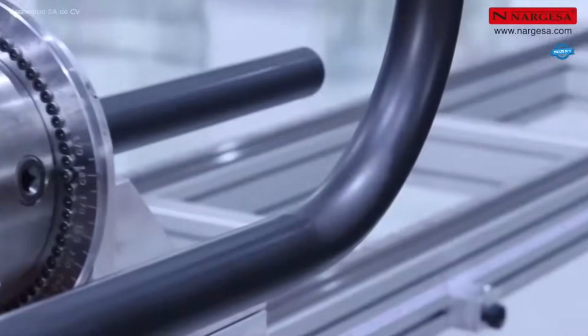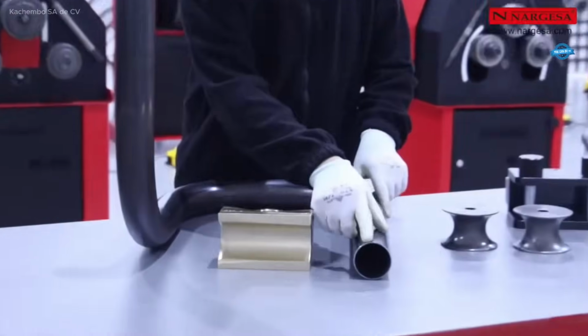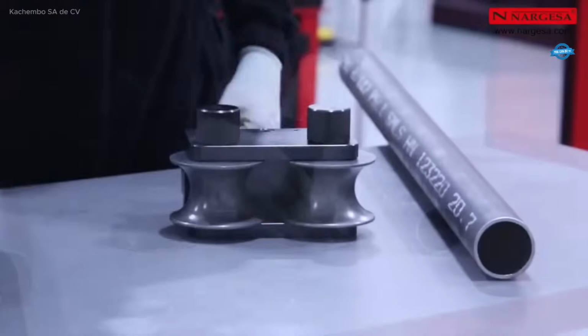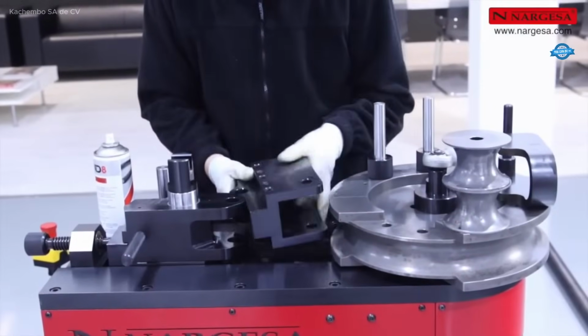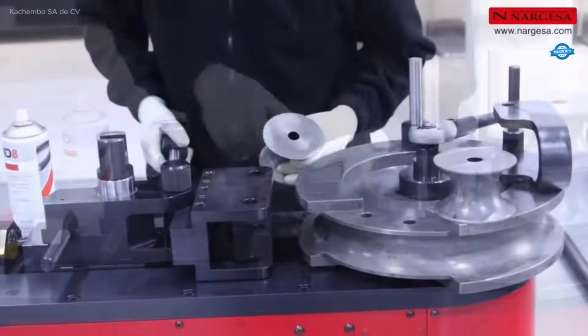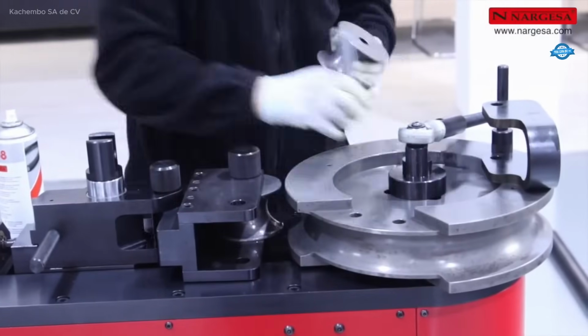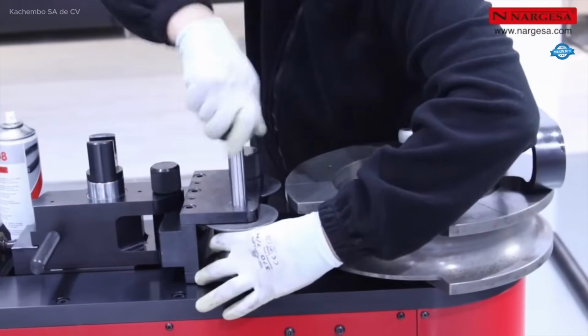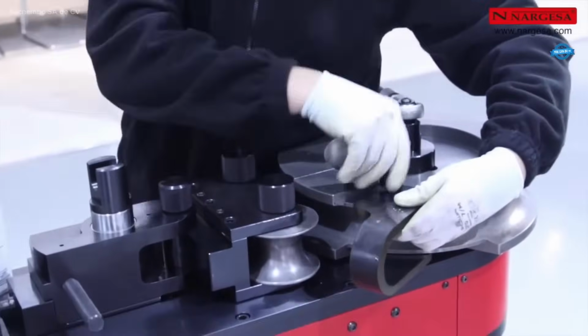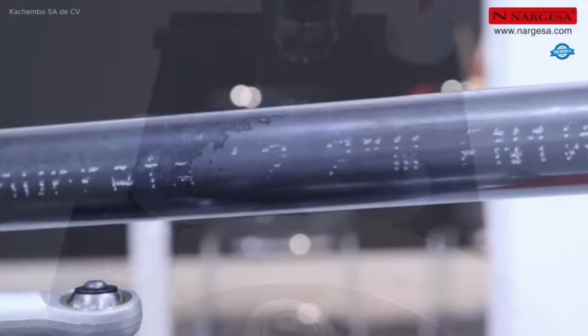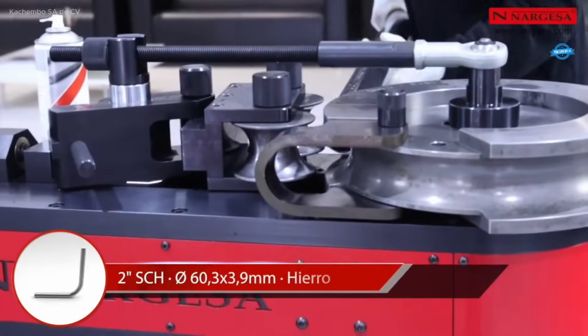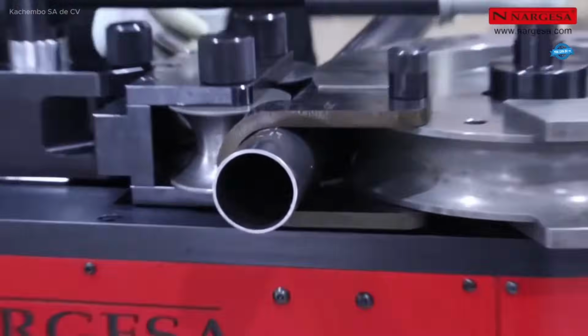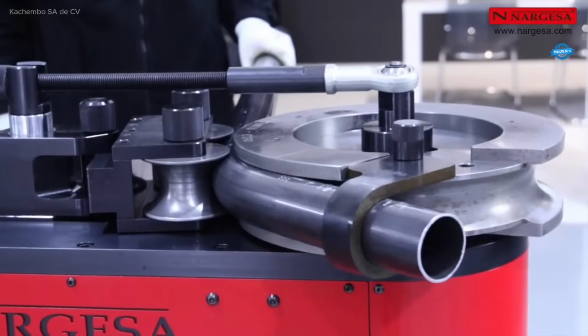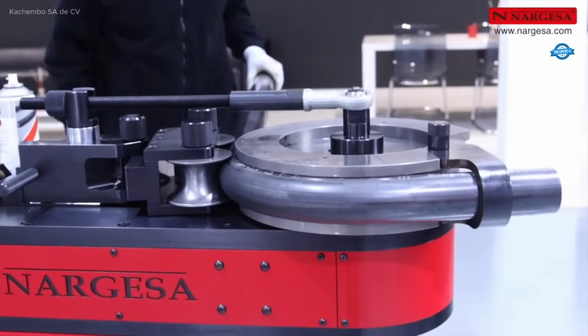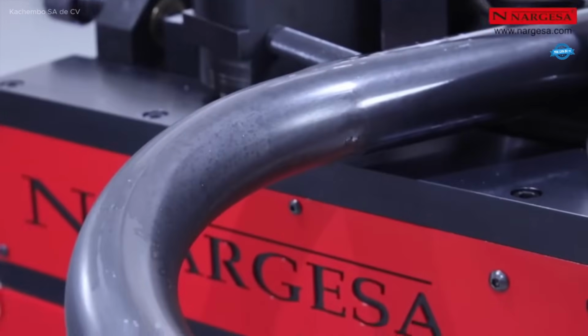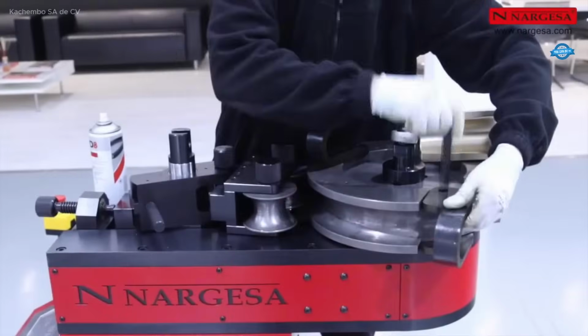The final project is the fabrication of a swimming pool railing using 42.4 mm diameter stainless steel tube with a bending radius of 127.2 mm. The tube development was calculated based on the drawing, adding the straight sections 100.8 mm, 1070.28 mm, 596.44 mm, 570.28 mm, and the length of the bends, using the coefficient K equals 0.01745 multiplied by the bending radius and the difference between 180 degrees and the inside angle of each bend.